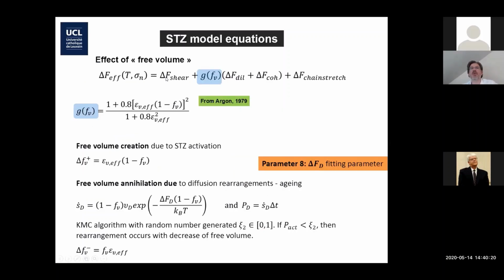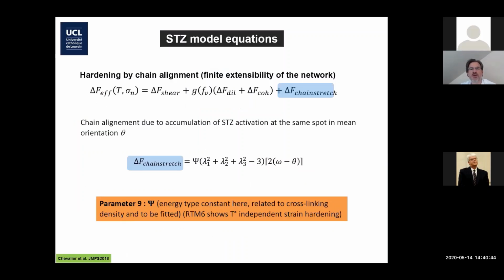I will skip the story about the activation volume and the free volume. We put it at the beginning to follow the work of Shu, but the recent analysis we've been doing, and Frederick Van Loock is looking at that, shows that it's a secondary effect for most of the predictions. So I propose to skip this. If you want to read more, you can read it in the paper. And we proposed a very phenomenological approach to take into account the hardening coming from the chain alignment, related to the stretches, introducing an extra parameter here, which has an energy form.